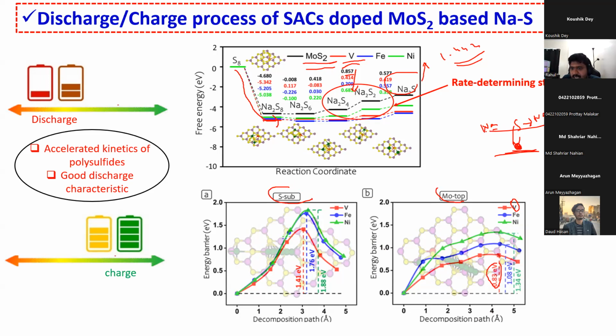This is the Na2S. So if the vanadium makes a very strong binding with the sulfur, then this bond can break related to this bond. I already told that vanadium has a much stronger binding energy because of its d-band center being closer to the Fermi level. That's because vanadium has a very strong binding with the sulfur. That's why the sodium bond will break. That's why we found that it has a very low catalytic barrier, so it can easily break the sodium-sulfur bond.